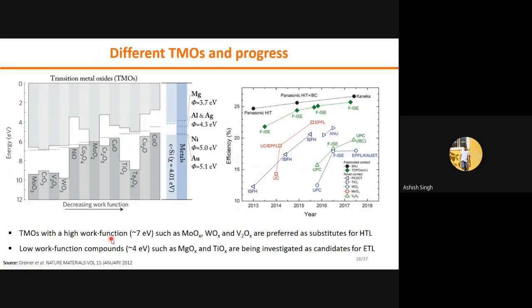If the work function of the TMO is in the range of 7 electron volt, that can be used for the hole transport layer. And if the work function is low, in the range of 4 electron volt, that can be used as an electron transport layer. So molybdenum oxide, vanadium oxide, tungsten oxide, tantalum oxide are used for the hole transport layer, while magnesium, titanium, and some fluorides are also used for the electron transport layer. And this is the efficiency progress of transition metal oxides. So the benchmark is, as we discussed, the HIT IBC solar cell made by Kaneka.